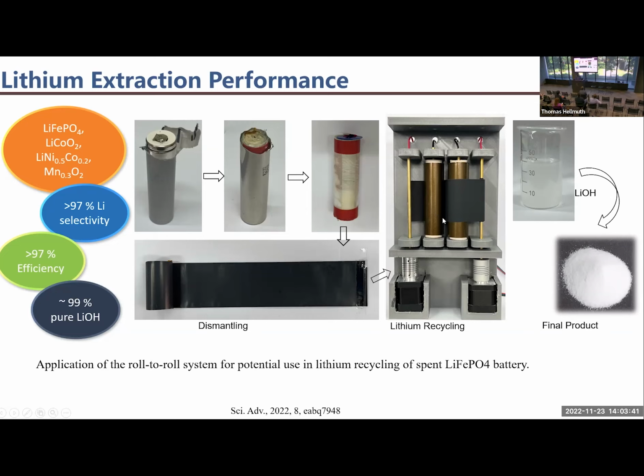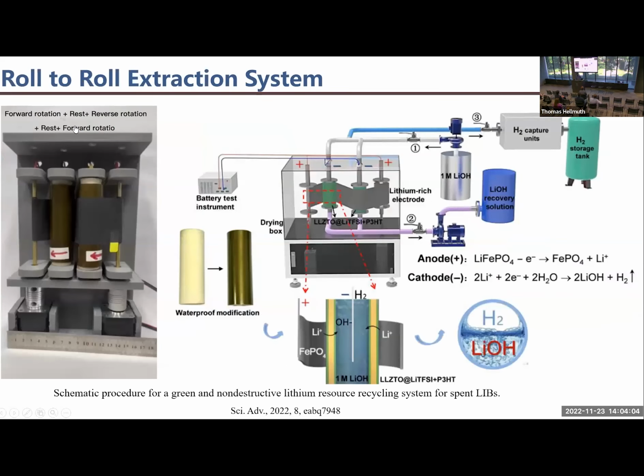So what we have here is a solid electrolyte basically in these columns. That solid electrolyte is exposed to the electrode. So the lithium from this electrode moves through the solid electrolyte, and then lithium hydroxide solution is passed through this column. And that one dissolves the lithium that is transporting from this electrode through this column to the liquid. And eventually we get this highly concentrated solution. This is a very attractive methodology. So this is how it works.